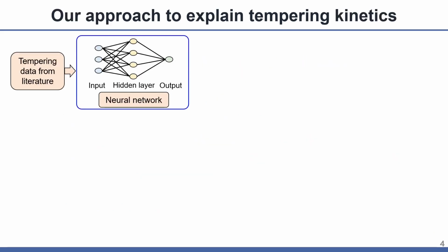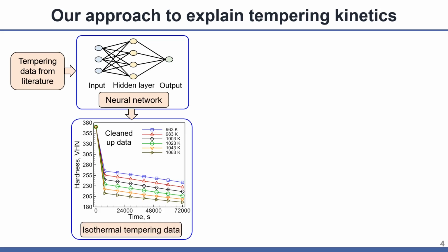In our approach to explain the tempering kinetics and resulting hardness variation, first a neural network was trained using tempering data on grade 91 steel collected from the literature. Then the trained neural network was used to generate high quality tempering data for various combinations of temperature and tempering time. The constants in the JMA equation were calculated using the tempering data obtained from the neural network.